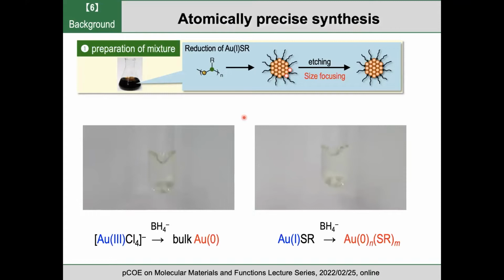So I show you our method to achieve this synthesis. The first step is the preparation of the mixture of magic clusters by chemical reduction in solution. So here is the movie after putting reducing agent into the gold 3+ ions. So you can see black powders. So we have basically bulk gold in solution without any protecting reagent.